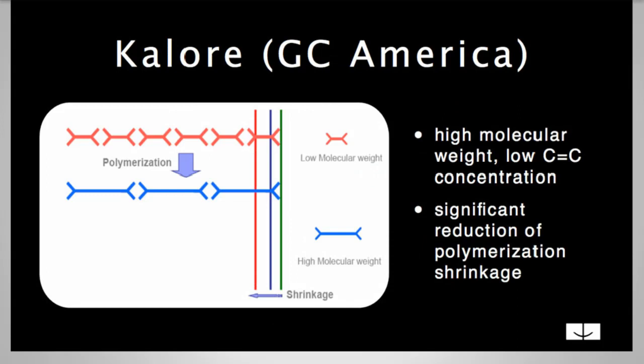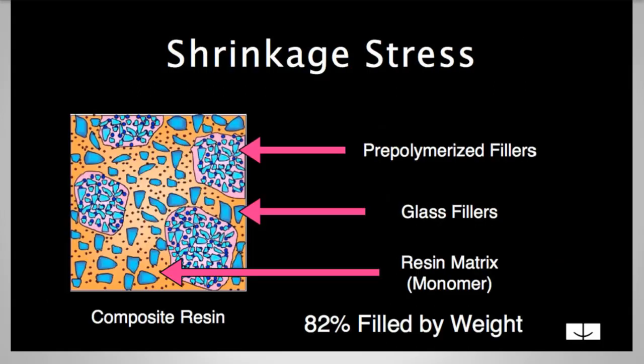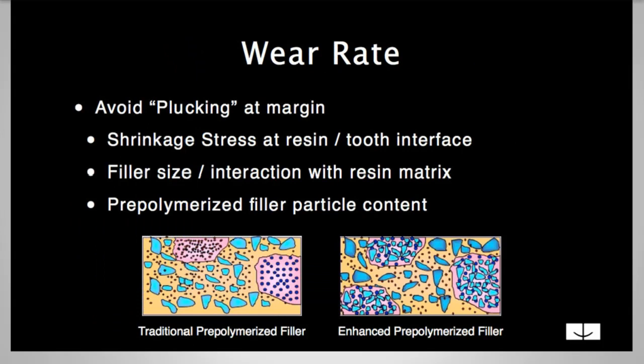Now when you talk about the wear rate of your composites, what you want to avoid is plucking at the margins. One of the things that you hear about is the white line around composites over time, and what can happen is that shrinkage stress can pull at the margin, and then bits of material, bits of the composite can be polished into that area if the shrinkage stress is too heavy. That's something that John Burgess talked about in the latest issue of the Journal of Cosmetic Dentistry.